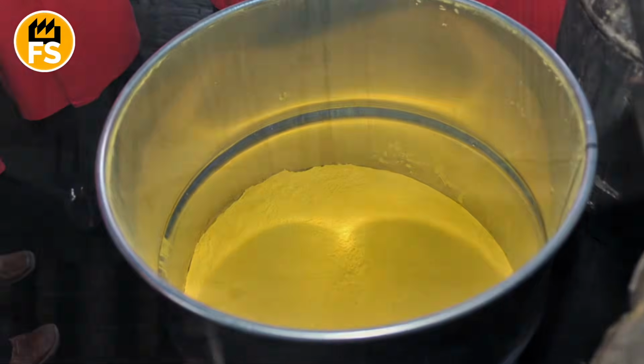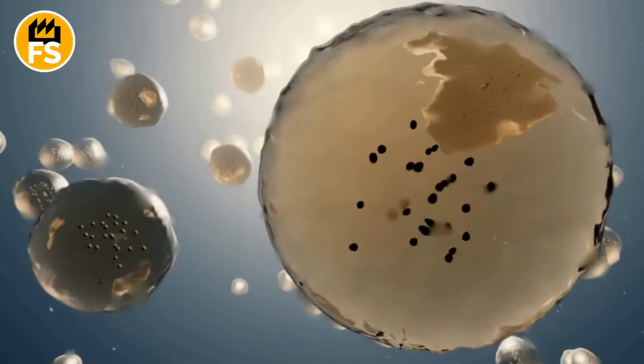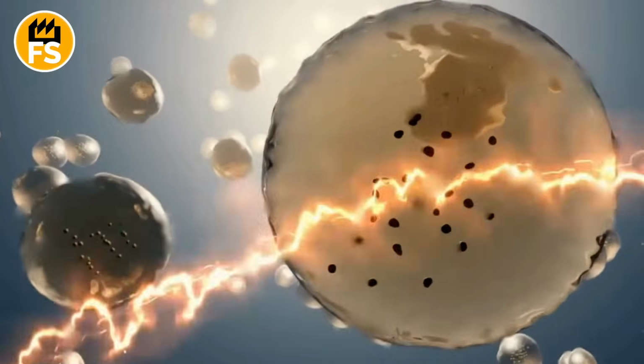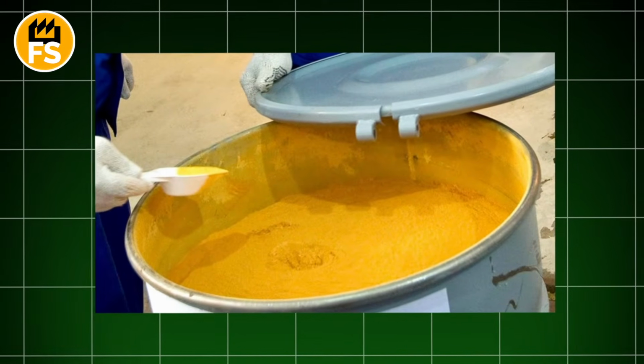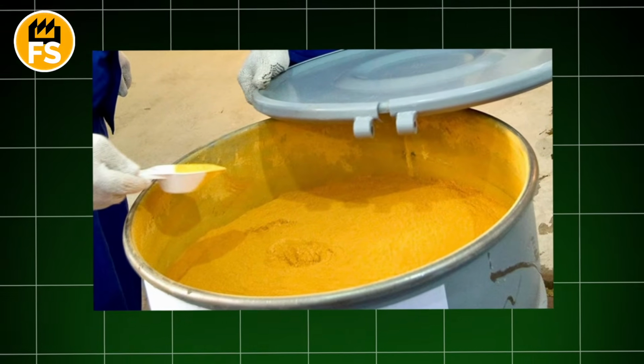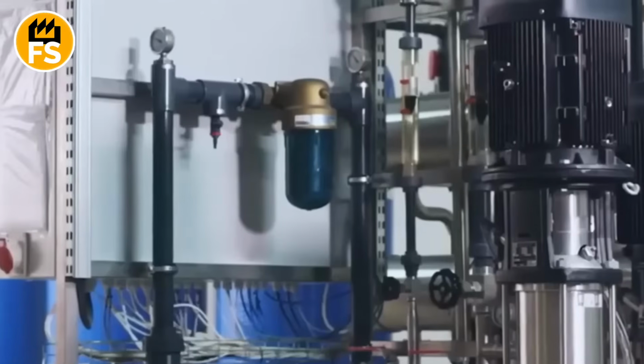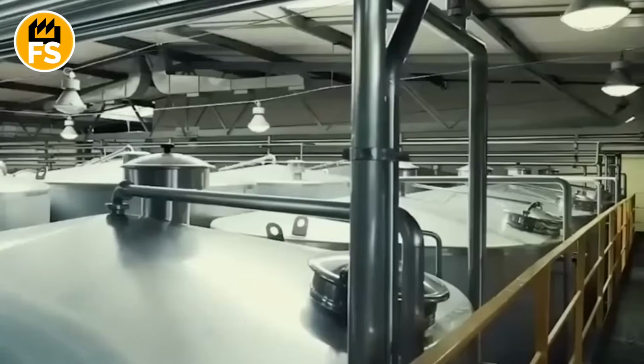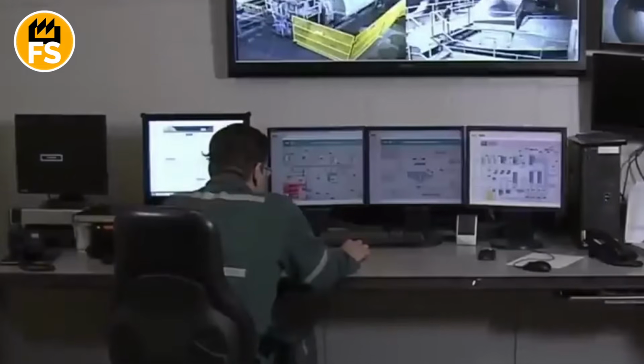By adding ammonia or hydrogen peroxide, the uranium is forced to fall out of the solution in the form of a bright yellow, thick precipitate. This precipitate is filtered, dried in furnaces, and at the output, we get the same famous yellow cake, a heavy, radioactive, mustard-like powder. This is the uranium oxide concentrate, the first step on the long path to clean energy.